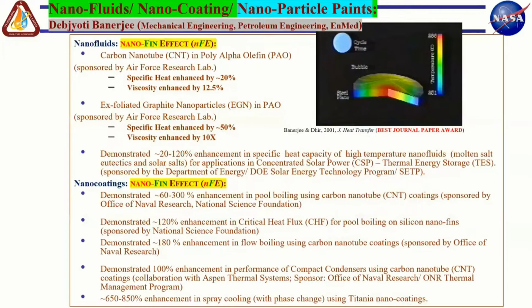The first part is, of course, on the nanofluids, and the genesis of this work was when I was a summer faculty in the ASME summer faculty program. I was visiting Air Force Research Lab, and there we were looking at polyalpha olefin, which is typically used as coolant for avionics components on the F-35 or the F-16 aircraft, for example. So the idea there was, if you take this coolant called polyalpha olefin and add nanoparticles at very tiny concentrations, the expectation was it would enhance the overall thermal conductivity of the mixture.